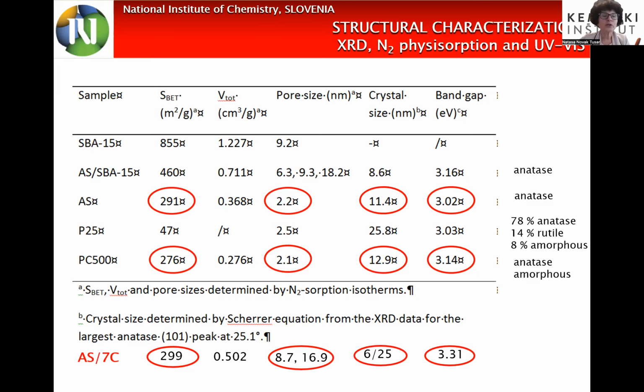But we combine, of course, the colloidal titania with colloidal silica in the synthesis procedure, and we got, as you see here, also very similar surface area, which is quite good if you compare it with the commercial titania, and a bimodal pore size distribution, which is actually also a very good characteristic, and also the crystal sizes are of 2 sizes, so 6 and 25 nanometers. So this material actually showed, as we will see later, also very good mechanical stability.